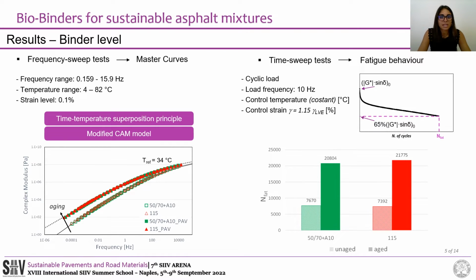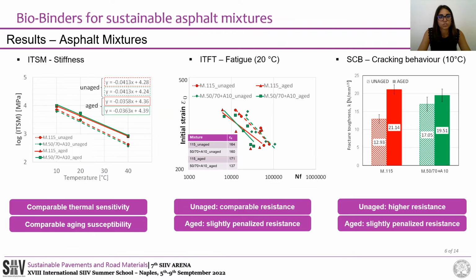Then, time sweep tests were performed to investigate the fatigue behavior of asphalt binders. They consist in applying a cyclic load at a selected frequency in control temperature and control strain, selecting a strain level higher than the linear viscoelasticity limit, thus entering in the nonlinear domain. The decrease of the loss modulus was selected as failure criteria. Results show again perfectly comparable performances both in unaged and aged conditions.